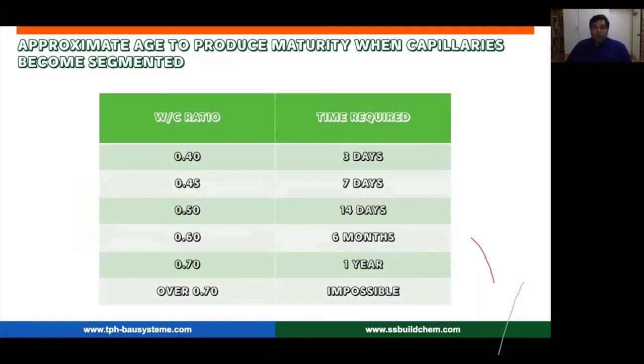So now, if we take a look at the impact of water cement ratio, basically good concrete is made with minimal water cement ratio. And if you keep the water cement ratio very low, say somewhere around 0.4, your capillaries or the porosity of the concrete becomes segmented in a time period of about 3 days, which is a very nominal time to do it.